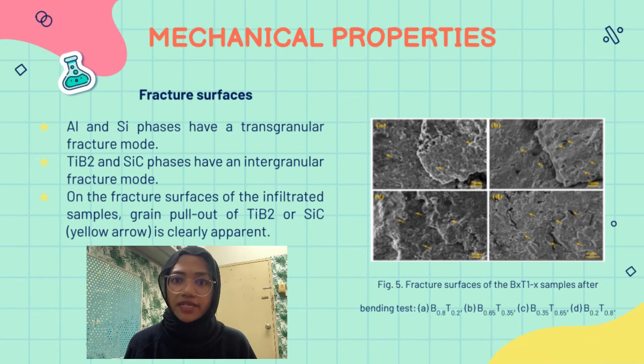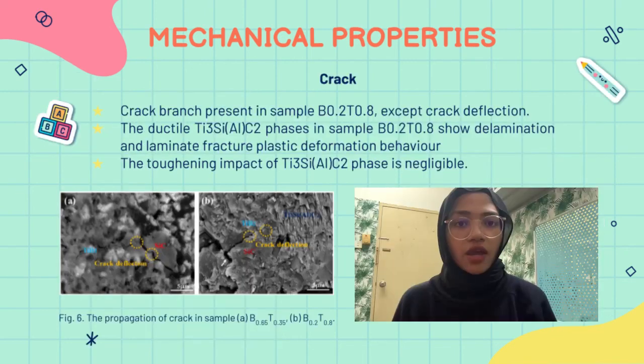in samples B0.8T0.2 and B0.65T0.35. Aluminium and silicon phases have a transgranular fracture mode, whereas the titanium diboride and silicon carbide phases have an intergranular fracture mode. On the fracture surfaces of the infiltrated samples, grain pull-out of titanium diboride or silicon carbide is clearly apparent. Crack branching is also present in sample B0.2T0.8 besides crack deflection.